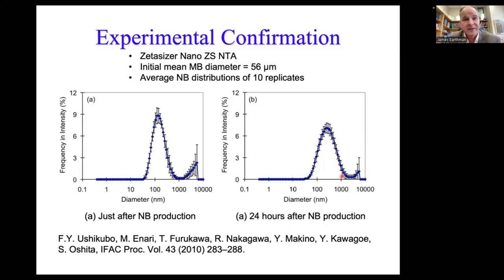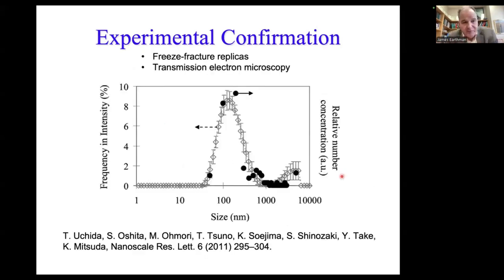I was pretty excited with that. Then we found another paper. This is by another group in Japan, different group. They created nanobubbles the same way with a large distribution of microbubbles. But in this case, instead of measuring using a light scattering technique, they use freeze fracture replicas. And freeze fracture replicas are really difficult to make. You have to have a very expensive machine to make them. But basically, what is done is you freeze a water droplet with, in this case, nanobubbles in it instantly inside this machine. And while the droplet is frozen, a wedge comes in, fractures the droplet, and then replica films are made on the fracture surfaces of that droplet.